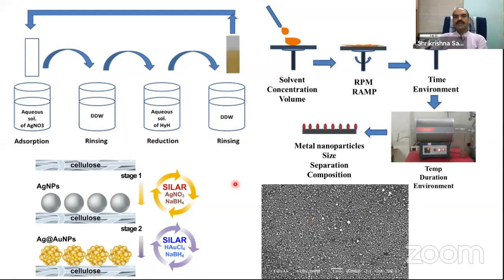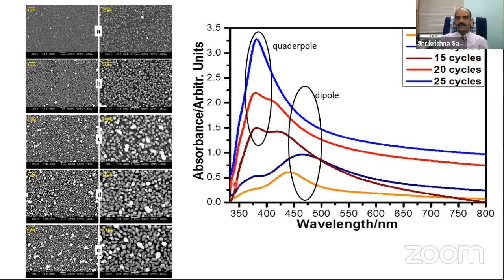I will not go into the detail, but you can see that these two techniques can be used. I'm going to show you now the same images of these silver nanoparticles grown by SILAR. What you can see is the surface plasmon resonance, the absorption with respect to this optical absorption spectrum. For the smaller nanoparticles, when you grow with 10 cycles, you are getting this dipole, and there is also a quadrupole, because this quadrupole tells me that some of the nanoparticles are attached with each other. And if you increase the cycles, this quadrupole is getting enhanced, and this dipole is getting diminished.